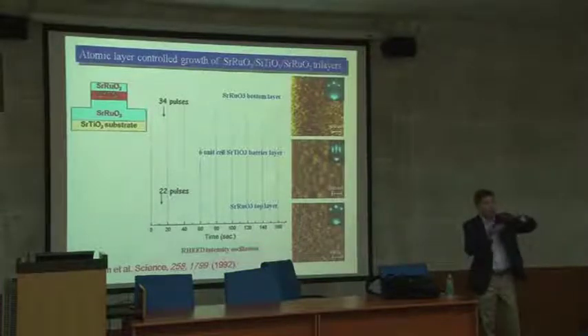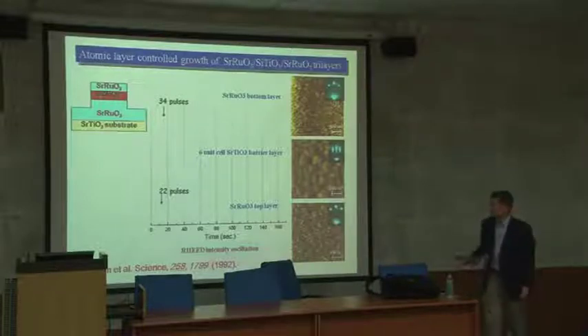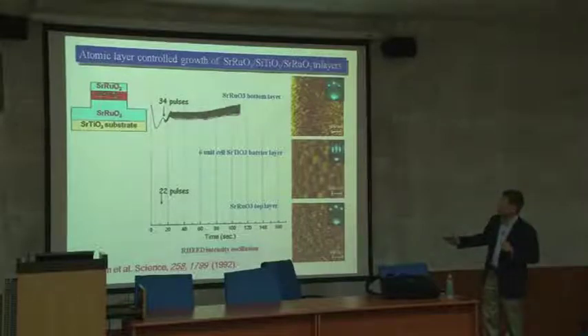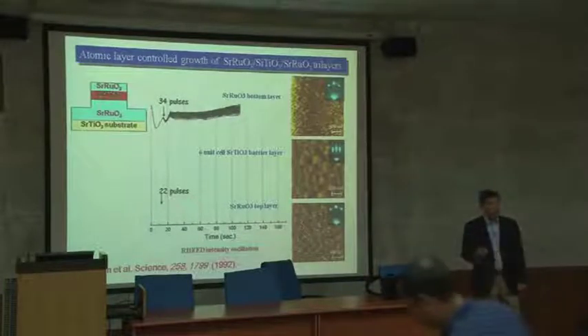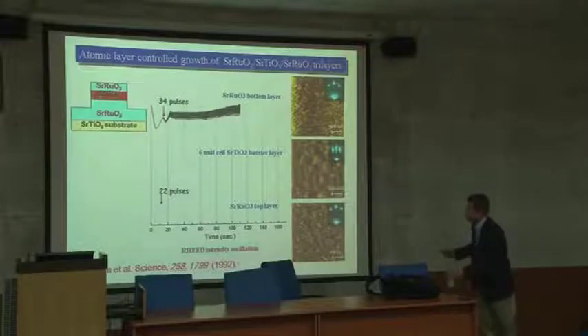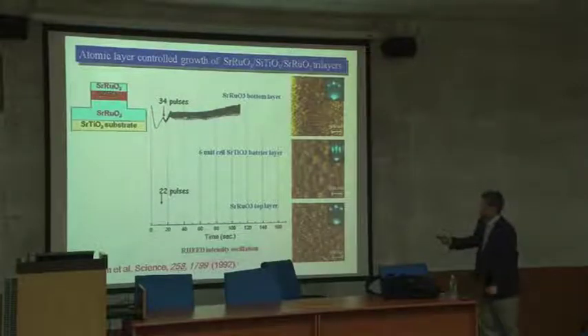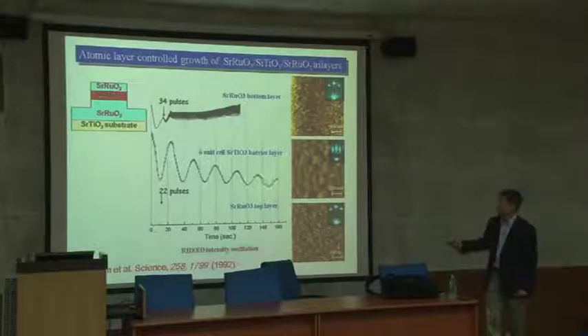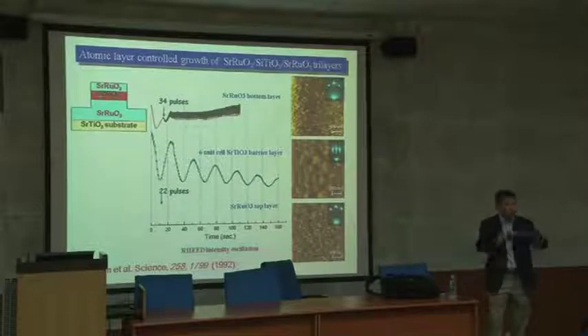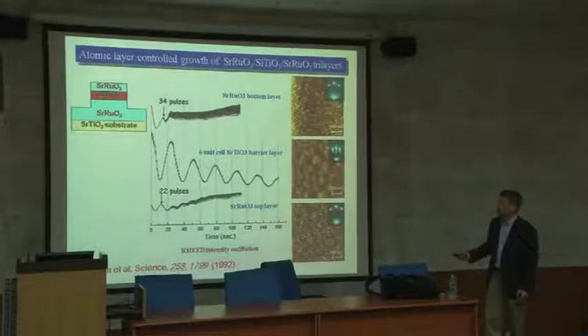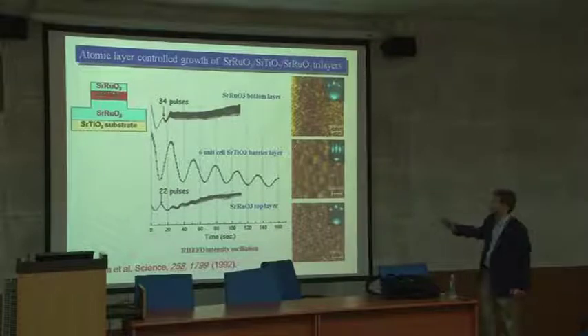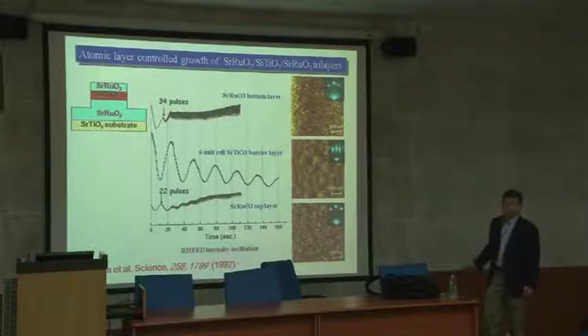ruthenate, a trilayer structure. Can you grow a trilayer structure? And you can make the first layer, okay, this is the bottom layer. Let me see the bottom layer here. There's the bottom layer. You see this kind of pattern? I'm going to talk about these details of the growth control in another lecture. And this is what we call step flow growth region. And strontium titanate grows like island growth, two-dimensional island growth. Strontium ruthenate goes back to step flow growth. I'll talk about that later, why this happened. And then, so anyway, you grow and maintain very nice step structures.